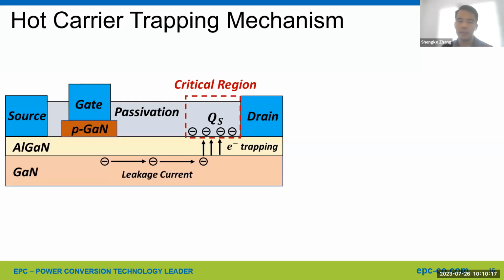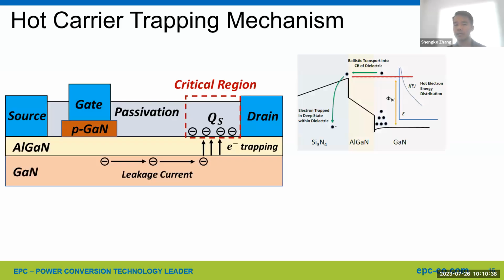Based on all the findings discussed, we developed a physics-based model to explain this hot carrier trapping process. So electrons in the 2DEG are accelerated by the high electric field and then scattered by the lattice and become trapped in the passivation film by the drain contact where those hot spots were seen. Now we align the band structure near the drain contact, where we can see an energy barrier that exists for the electron to overcome.